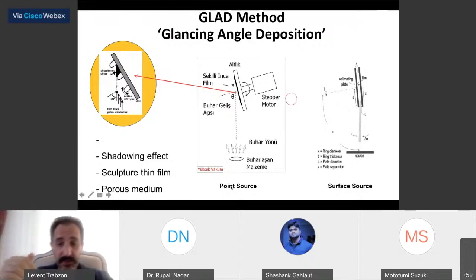But on the other hand, we have just seen a very nice talk given by Dr. Gonzalez. The surface source has also been utilized. But the mechanism and dynamic environment are very much different from the point source, so you should be very careful in using the surface source, specifically by means of sputtering GLAD film depositions.